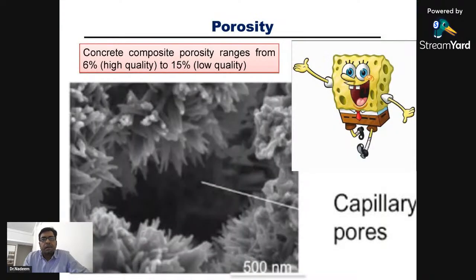So we have porosity. Naturally, we can't avoid porosity because OPC is being used. It reacts with the water, giving us CSH along with an unstable compound in the form of calcium hydroxide. 50 to 60% of the water is used in the reaction. The rest of the water evaporates, which creates pores. Naturally, in high grade concrete, porosity is on a lower side, maybe in the range of 5 to 6%. But in low grade concrete where the water cement ratio is not being controlled, porosity is as high as 15%. Both things we need to address if we want a long lasting concrete.